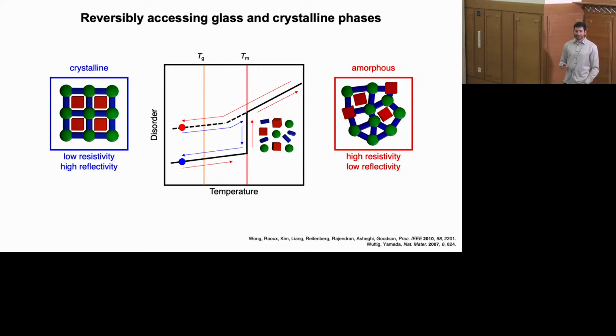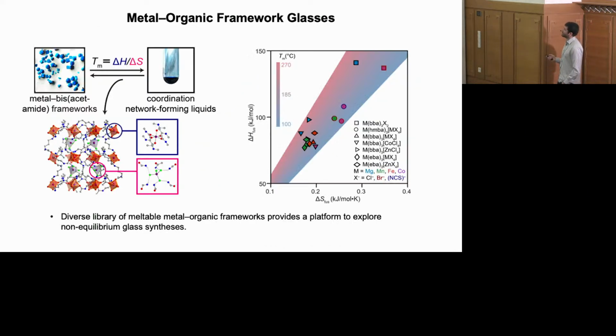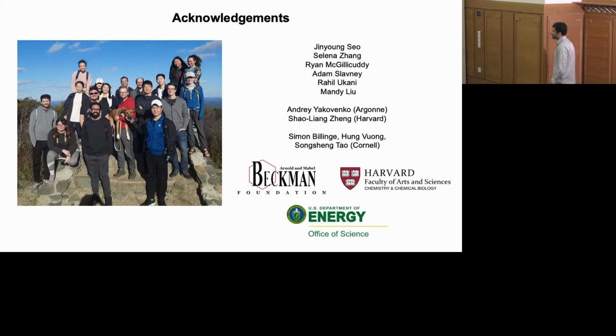This is typically done with chalcogenide alloys. These are the most common types of phase change memory-based materials, but these require melting temperatures of above 700 degrees C, which requires a lot of energy to use them. And so there's a lot of interest in being able to do this at much lower temperatures. And we think that our materials provide access to that regime, and we're really excited about exploring their potential for this kind of application. So hopefully that was a taste of some of the different kinds of more thermodynamic-y research that is happening in my group.